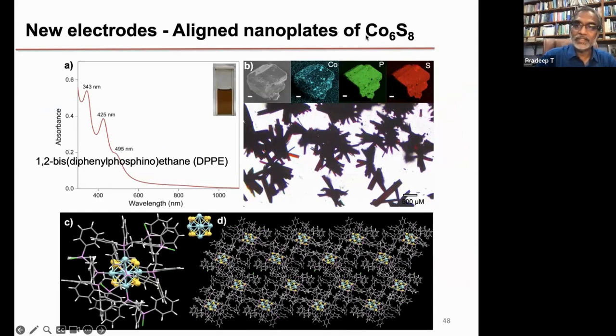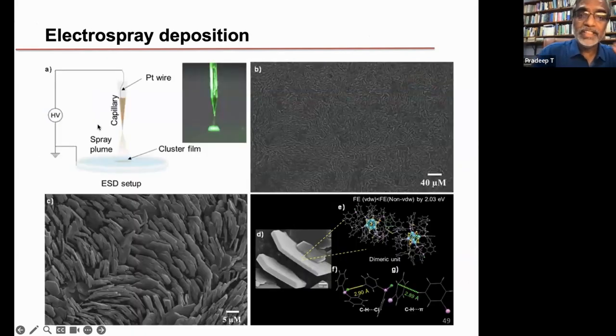So here is a cluster, an atomically precise cluster we make in the laboratory. We make crystals of these, and this is how it looks in single crystal diffraction. But if you take a solution of these clusters, which are actually soluble, and pass it through a capillary under an electric field, you can create micron scale droplets, which are charged, containing these clusters, and you deposit them on a substrate. In this particular case, it is liquid water. You create materials of this kind. These are plates, and these plates look like this. There is, of course, a collection of these plates.